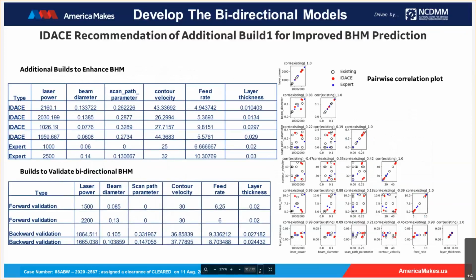For the additional builds, this is a quick demonstration of the additional builds. We have finally selected 4 IDACE builds and 2 expert builds. And we also recommended 4 walls. 2 walls are aimed at forward prediction and validation, and 2 walls are aimed at backward validation. All these walls have been carefully examined from the pairwise plot to ensure spatial coverage and also pass the buildability constraints. And in the later results demonstration, I will show the model refinement validation and also the difference in the uncertainty. So next slide, Neil, please.